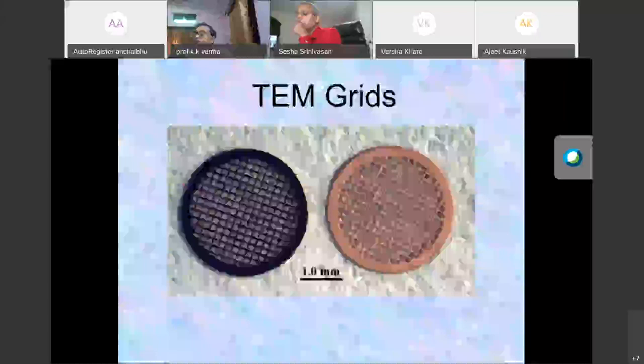I will show you the picture. This is the TEM grid. This is especially the copper grid, which has a coating of polymer. On this polymer, you put your sample. So you see, this is the sample, a magnified view of your TEM grid, on which you have a smaller black region where you have a sample, and there is a mesh of copper which holds this formvar coating.